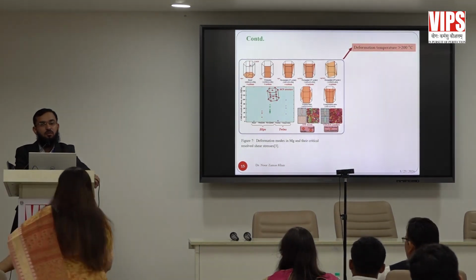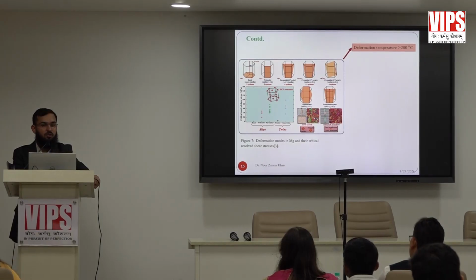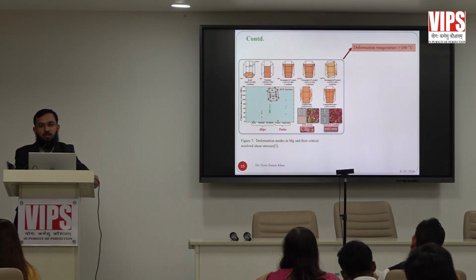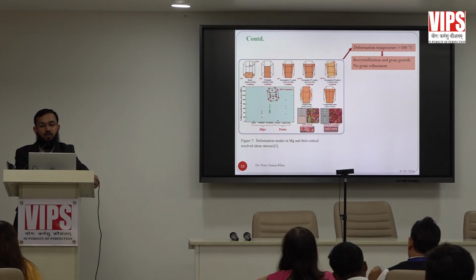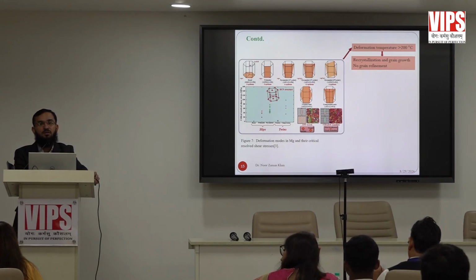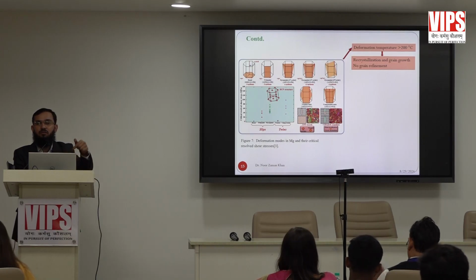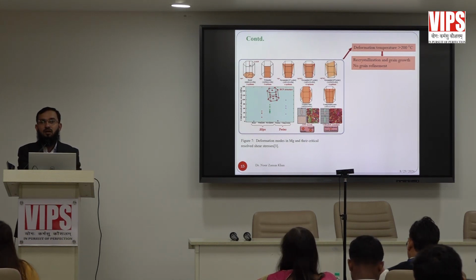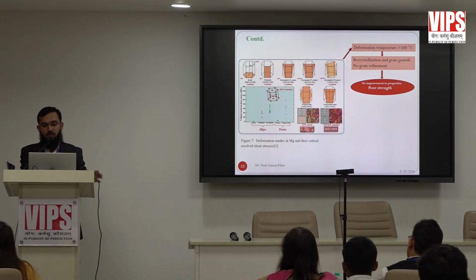If you want to activate slip systems, you have to increase the temperature. It should be more than 200 degrees centigrade. Now what's the problem? If we increase the temperature of magnesium above 200 degrees centigrade, it will lead to grain growth. And if you have ever heard about the Hall-Petch relationship, if the grain size is larger, it will reduce the hardness and strength. Due to grain growth, grain size will increase, and it will decrease the mechanical properties. So on one side you are activating the slip system, on the other hand you are reducing the strength. But we require to enhance both the strength and the ductility and deformation.